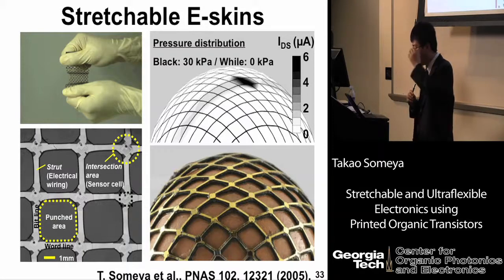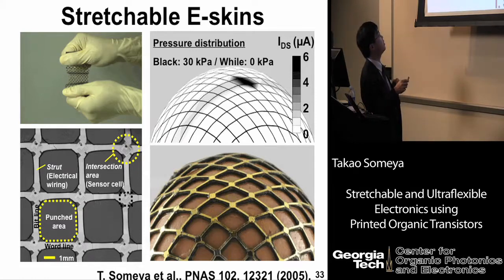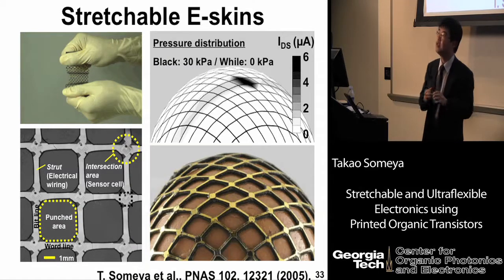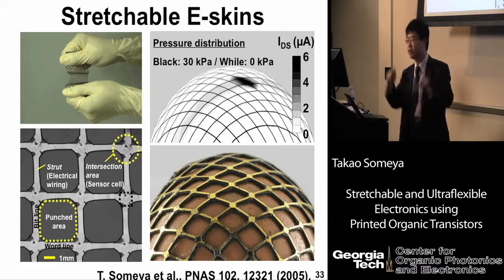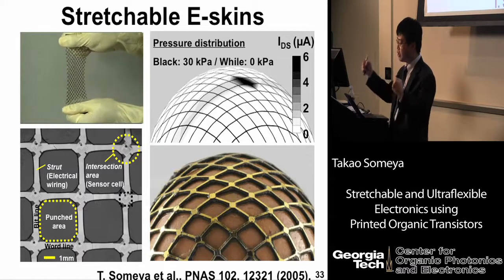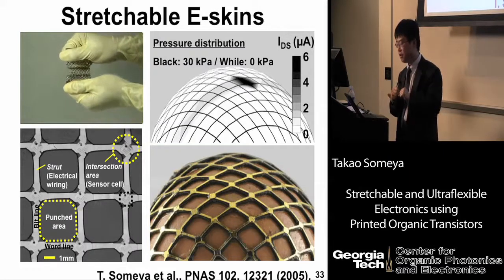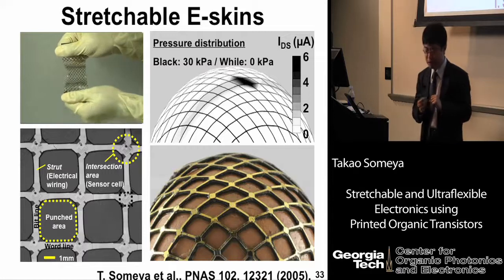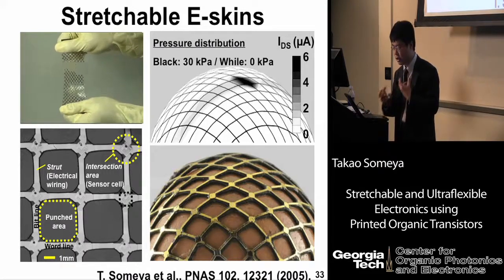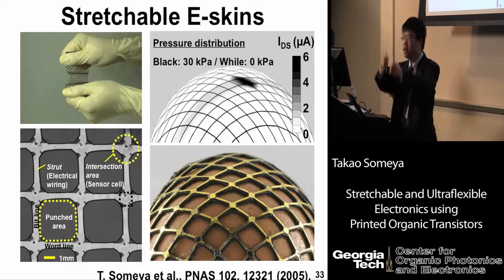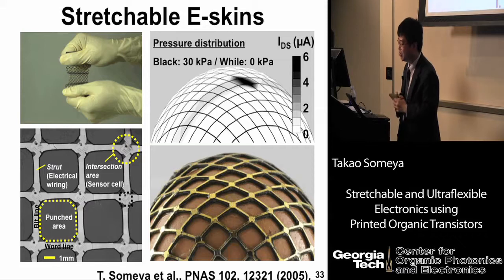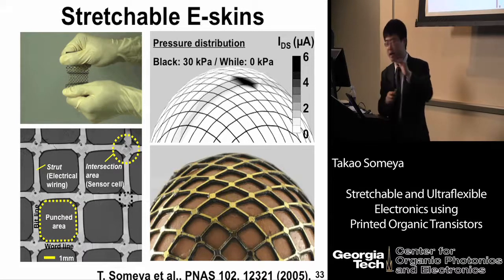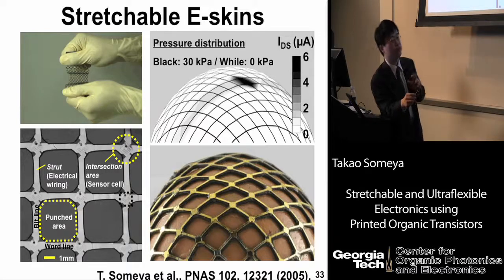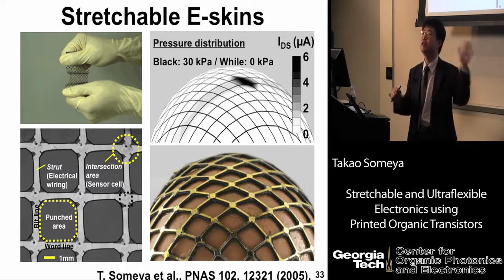After fabrication of flexible TFTs, we remove the unnecessary region, like this. At the intersection area, here is one sensor cell comprising one organic transistor and one pressure sensor. By using novel net-shaped structures, we have made a stretchable robotic skin, which can be stretched by 30% without causing any mechanical degradation. Now we stretch our E-skin and apply it onto the surface of an egg. If I apply pressure somewhere here, we can obtain the pressure distribution in this device geometry.